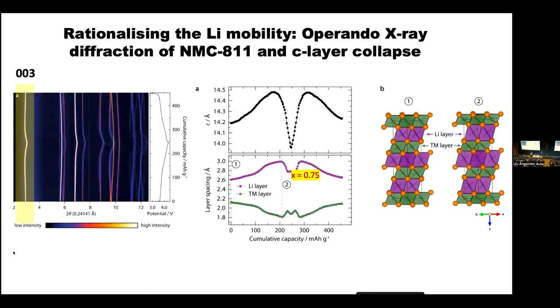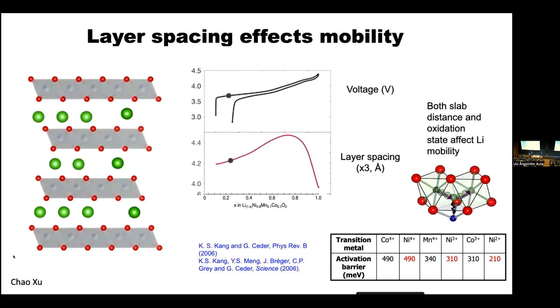So how do you rationalize this? Those of us who work on these layered cathode materials are very familiar with the phenomenon of the spacings between the C layers, which define the interlayer spacings, going up first as you pull out the lithium. And then there's this dramatic collapse at about x equals 0.65, as the layers come on top of each other. You can decompose that into the collapse in the lithium layers and the collapse of the transition metal layers. And you can see that the lithium layers collapse at about 0.75. And that's when the lithium motion starts to slow down.